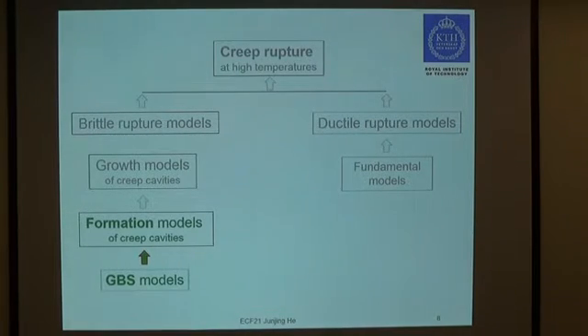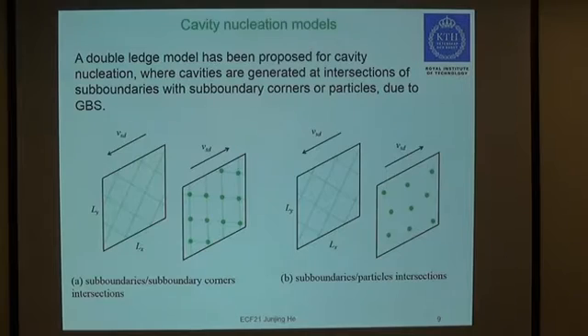With the grain boundary sliding models, it's possible to propose the cavity nucleation models. A double-ledge model has been proposed for cavity nucleation, where cavities are generated at intersections of subboundaries with subboundary corners or particles due to grain boundary sliding.